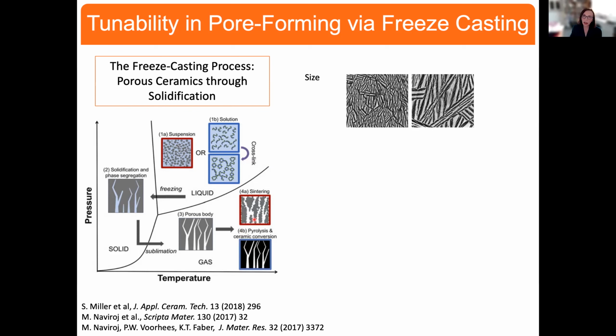So one of the things in terms of this tunability that is almost intuitive is that the pore sizes are going to depend upon how fast you conduct this solidification process over here. So if you freeze really quickly, the diffusion lengths are pretty small, and so you end up with small pores and relatively small pore walls. If instead this freezing front goes through the material pretty slowly, we're basically allowing the system to have more time for that separation between the fluid and the pre-ceramic polymer or the powder. And so you end up shown here with larger pores and larger pore walls.